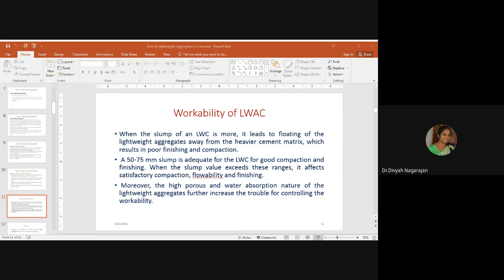Studies have reported that a slump of 50 to 75 mm is adequate for lightweight concrete for good compaction and finishing. When the slump value exceeds these ranges, it affects satisfactory compaction, flowability, and finishing. Moreover, the highly porous and water absorbing nature of the lightweight aggregates further increases the trouble of controlling the workability. Coming to density, the lightweight concrete has a maximum density of 2000 kilogram per meter cube, and it can also be achieved by using low density aggregates.